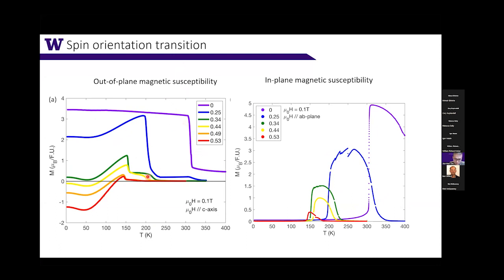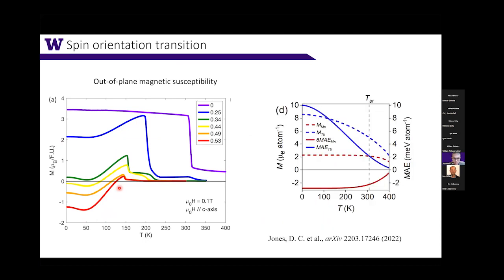For the lower doping, you see something similar to the parent compound, with an increase of magnetization. But you also see a decrease of magnetization as you go to lower temperature. For the higher doping, this decrease becomes more and more prominent, and you even see negative magnetization, a negative magnetic response at the lower temperature. Namely, you apply a small field and cool down, and the magnetization goes in the opposite direction to what you initially applied. So a very strong diamagnetic response. How do we understand this?